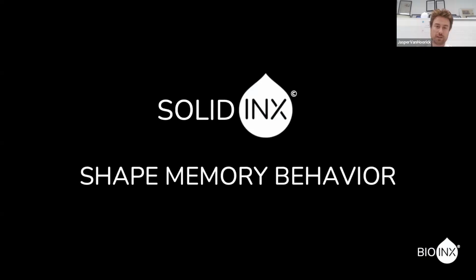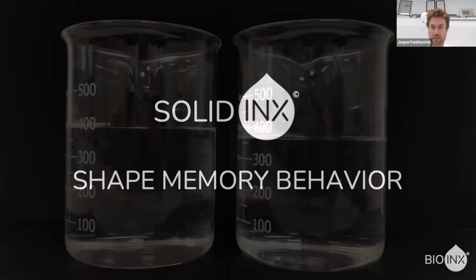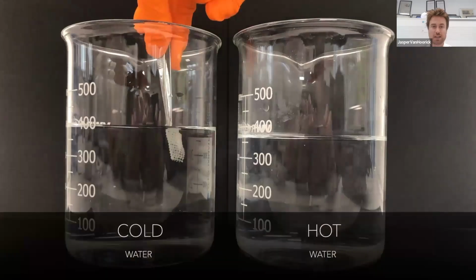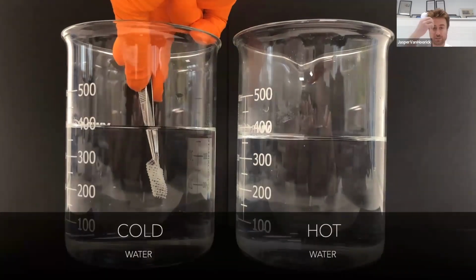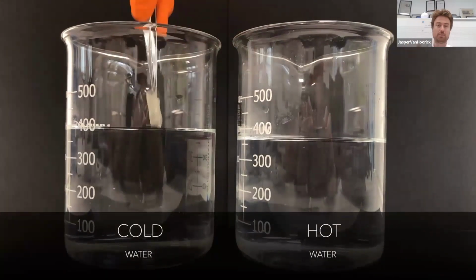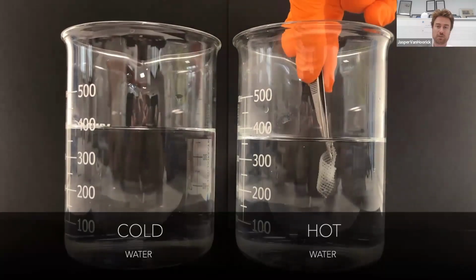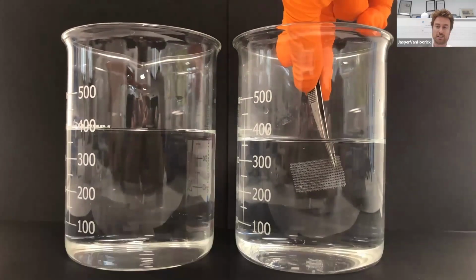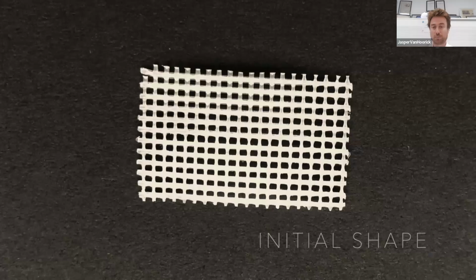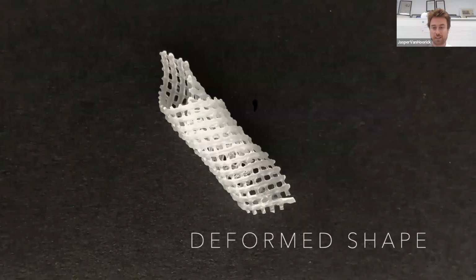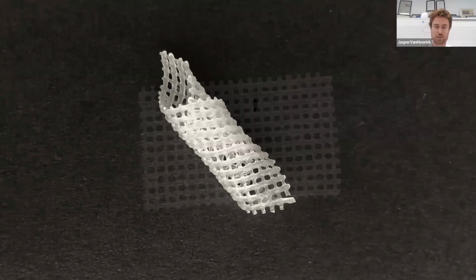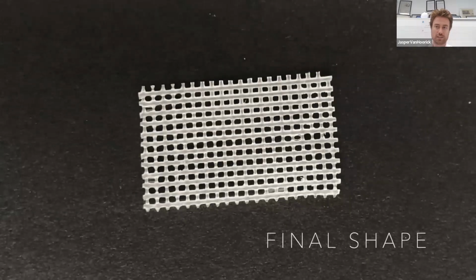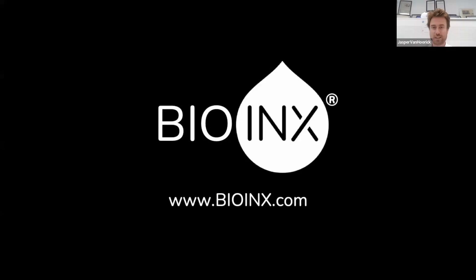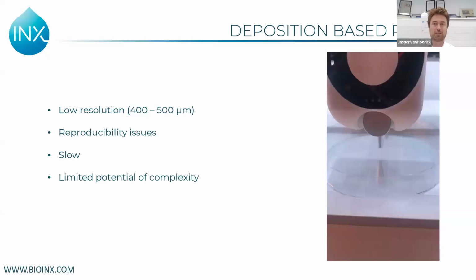And the last thing is you can play around with the polymer. You can, for example, introduce some cues which allows modification after printing. So for example, you can use shape memory materials, which you can deform after printing. And then if you reheat them or put the trigger on there, you can change the shape after printing, leading to 4D bioprinting, where you can have an additional dimension there. This is, in a nutshell, deposition or extrusion-based bioprinting.